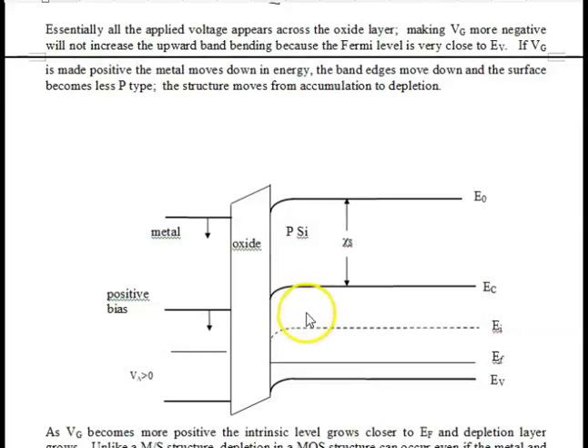So I put a field which is plus over here and minus over here, which is to say in the negative direction. Plus, minus points from right to left. Therefore, the flat band voltage would be negative. And that is always the case for a situation in which in equilibrium we have a depletion in the silicon. That means that the metal work function is less than the silicon work function. Flat band voltage will always be negative, and we saw, for example, if we had an N plus degenerately doped metal for the gate and a P silicon of 10 to the 17th doping, the flat band voltage is about minus, emphasize the word, minus 1 volt.